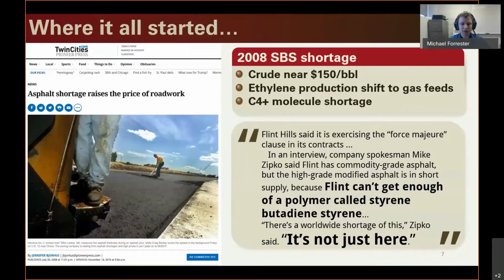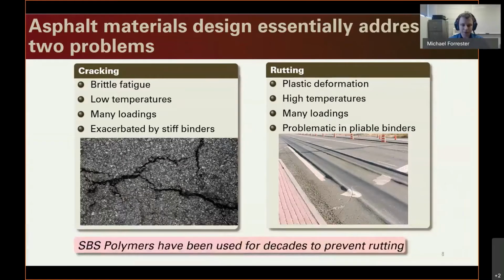And there were some huge supply chain logistics issues that came up, especially back in 2008. Most asphalt companies couldn't get their hands on SBS, and it caused a huge issue in the paving world because a lot of the pavements that needed to have polymer weren't modified with polymer, and it caused all kinds of issues. Predominantly, those are related to the cracking and the rutting of the roads. So polymer can help with both of these things.